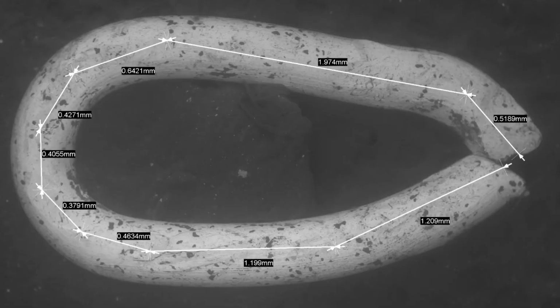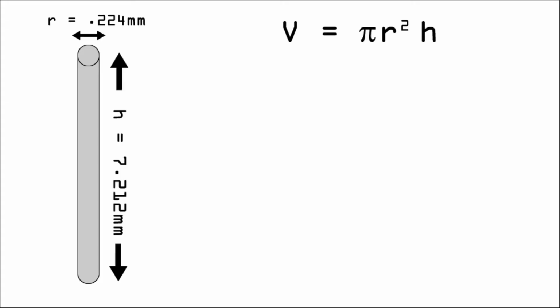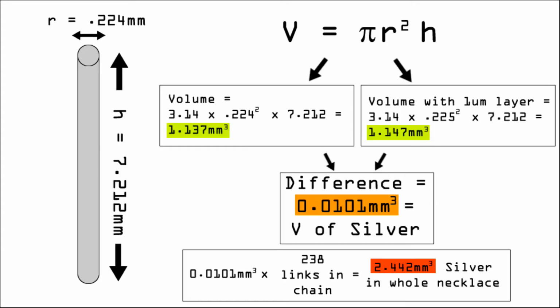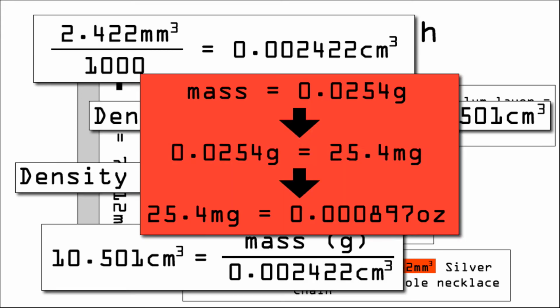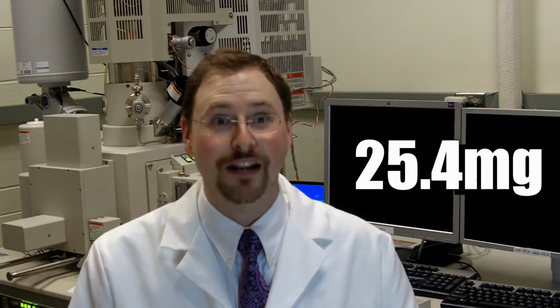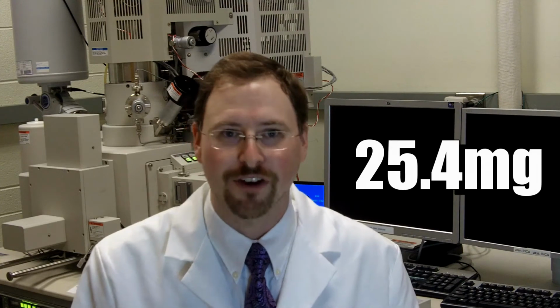Well, here's what I did. I assumed that each link in this chain was a cylinder. I found out the approximate diameter and length of that cylinder and was able to calculate the volume of a 1 micrometer thick silver layer. And then more math. I ended up with about 25.4 milligrams of silver contained in this whole chain.